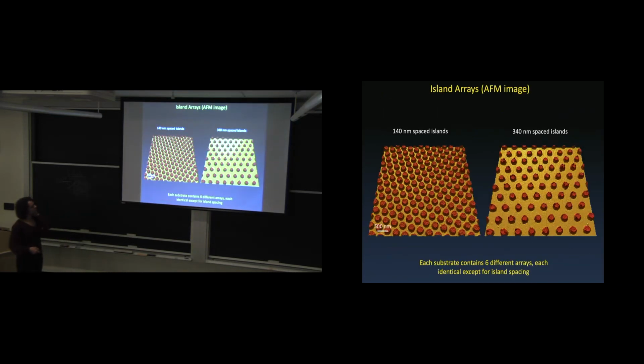Okay, so the first thing we did is make different substrates with just different island spacings on them. We did triangular arrays so we could increase the spacing without changing any other parameters in the system. We made one chip, and each chip had 6 different spacings on it. Everything else was identical.